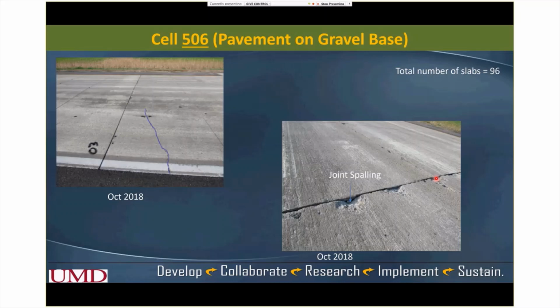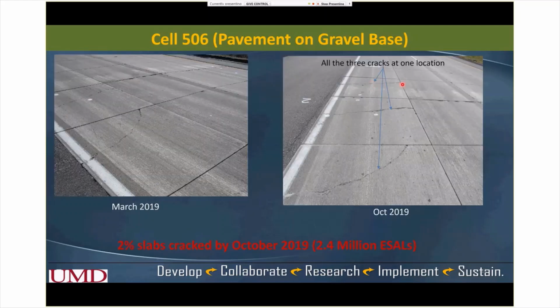So by October 2019, a couple more cracks formed. Still, until the last survey was conducted, or the data whatever I have, I know there are 3 cracks in this cell, no other cracks. So 2% slab cracked by October 2019 after 2.4 million ESALs, which is great, I would say, because these 5-inch thick slabs were actually constructed for the low volume road, and only 2% slab cracked after 2.4 million ESALs, which is really great. But we'll have to keep in mind the base layer is really strong, 11 inches of aggregate base.